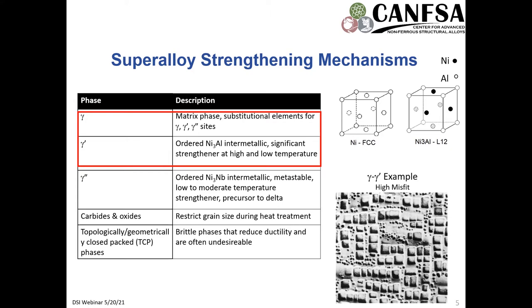And other alloys that you may be familiar with, such as Inconel 718, have gamma double prime, and this is a metastable Ni3Nb intermetallic. However, that decomposes at higher temperature exposures to delta phase, and this generally provides low to moderate temperature strengthening. And there are carbides and oxides that are present within the material. Previous studies have really shown that this doesn't don't have a significant effect on the microstructural evolution from the perspective of abnormal grain growth. However, those definitely are present in this material.